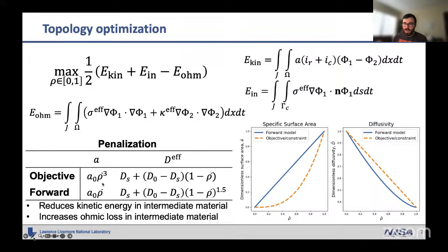So the energy stored is penalized where we have a rho to the 3 in the objective, so that the energy stored in the intermediate material is lower, and then for the ohmic losses, we make diffusion and conductivity with this 1.5 inside the forward PDE, so that the ohmic loss calculation overestimates the ohmic losses in intermediate material. So you can see the plots here.